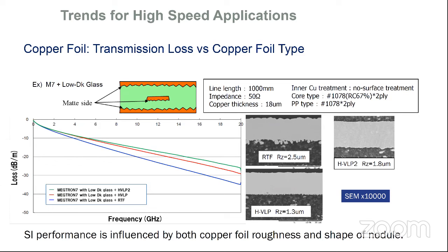So again, we've kept the resin system a constant. We've kept the glass reinforcement a constant. All we've done is manipulate the copper foil type. As you can see, the green line on the top represents the HVLP2. Then the red, accordingly, is the slightly higher profile copper, and then the RTF down at the bottom. So this is just a little graphical representation of the contribution of the copper foil roughness, with your impedance requirements and your resin system constant. This does give you a good separation of what occurs on your signal integrity and its effect from the copper foil roughness.